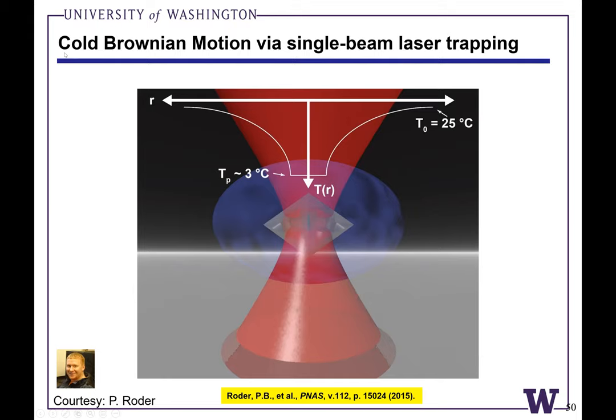So this is the first example of cold Brownian motion, so-called cold Brownian motion, since Einstein first explained Brownian motion at isothermal conditions back in 1905. And this was a really exciting result, that we weren't sure if it would work. You know, maybe the water would dissolve away the crystal, maybe the water would absorb more photon energy than the crystal could cool. And the experiment showed that we could cool this crystal at atmospheric pressure in water.